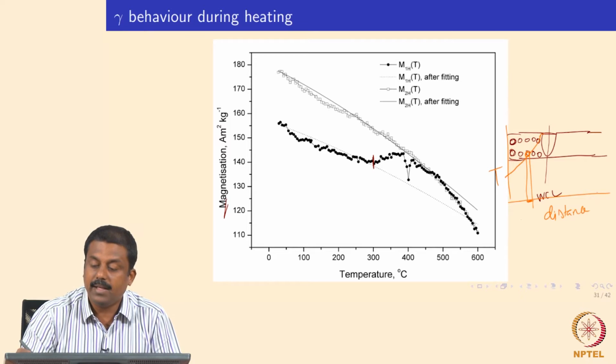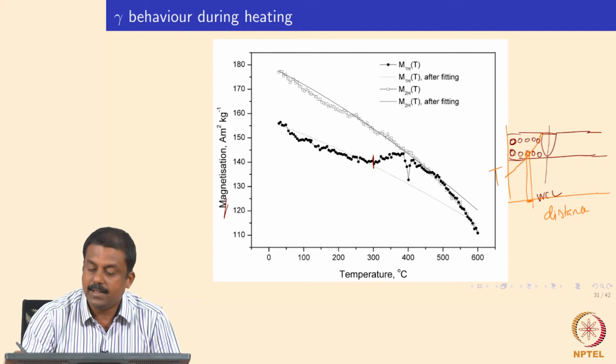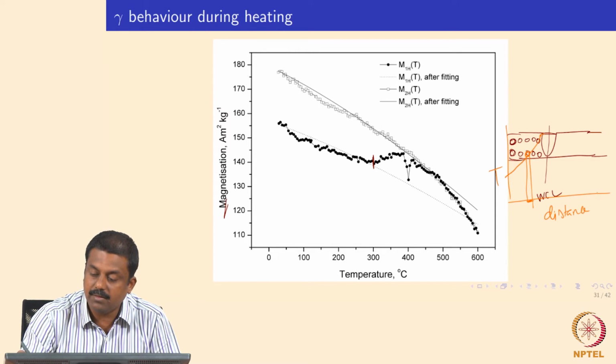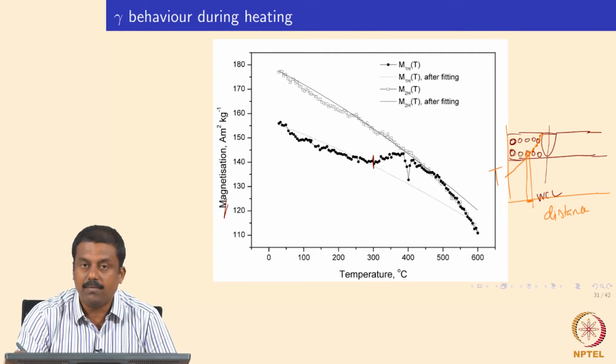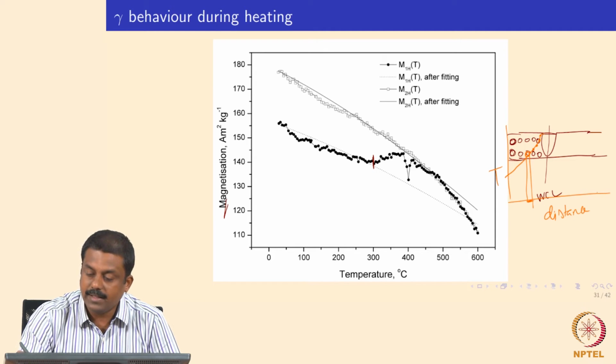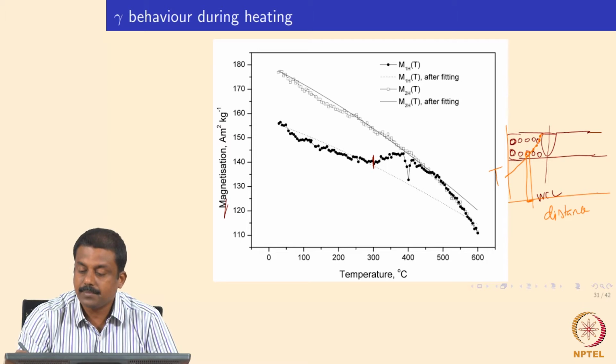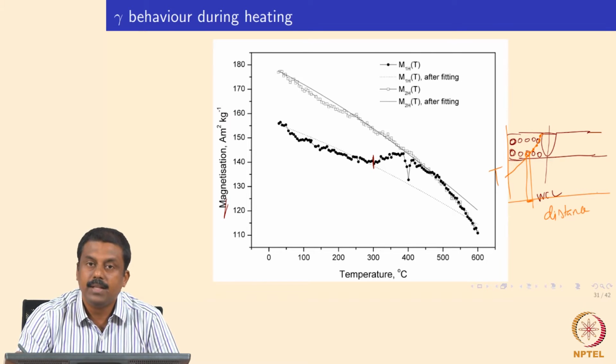If you want the effect of peak temperature on the retained austenite fraction, we need to measure with much finer resolution, is not it? For example, when you measure at a given location, the temperature should not vary by more than, say, 5 Kelvin. If that is the case, then we will have to make the measurements on a very small area of the sample.